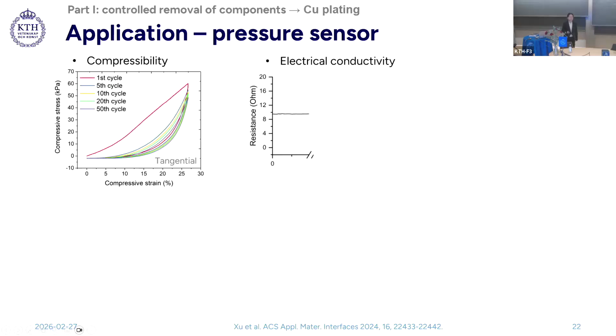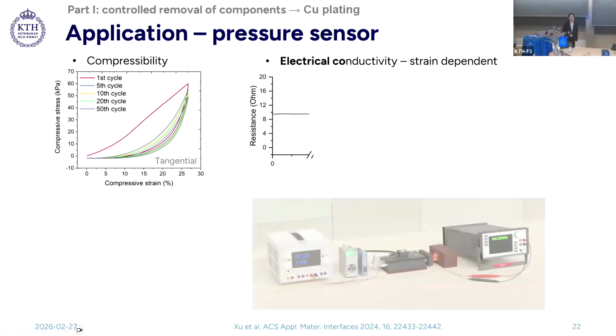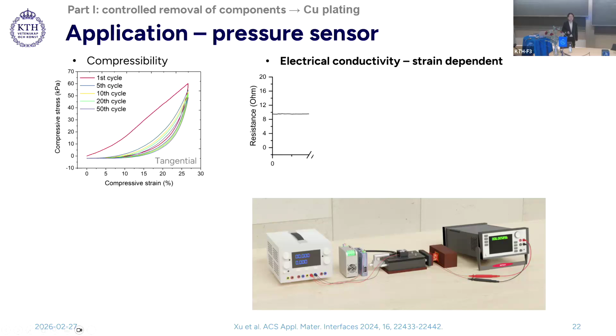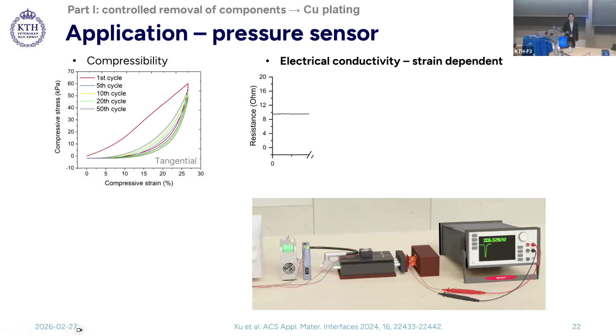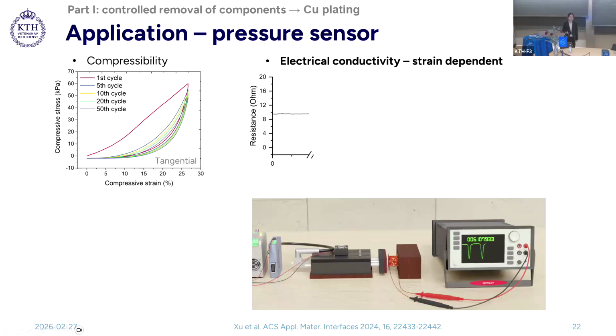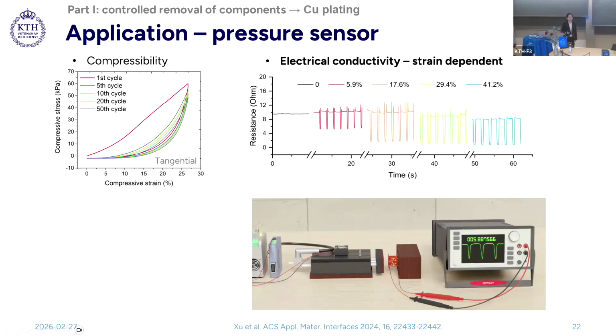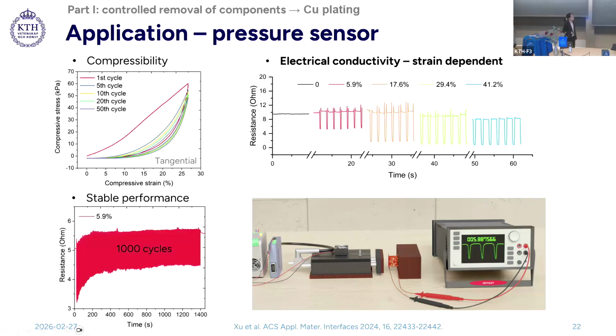If we combine these two features, a strain-dependent electrical connectivity can be achieved. Increased strain will decrease electrical resistance due to additional connective pathways and increased material density. Different strain leads to different electrical signals, making the copper-plated wood promising as a stress sensor. Besides, the wood-based stress sensor shows quite good and stable performance over 1,000 cycles.